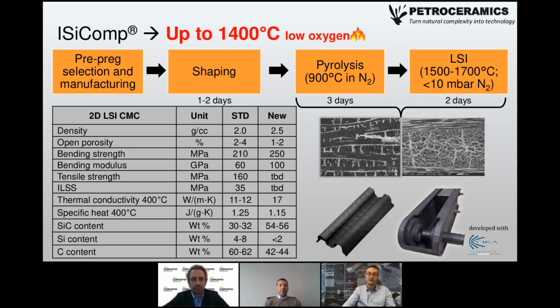So moving to higher temperature application, we have one of our leading trademarks, ISiComp. Also, in this case, we select the material and perform all the steps of processing from molding to conversion into a carboceramic matrix composite. In this case, after pyrolysis, densification is obtained by means of liquid silicon infiltration, which is faster and way cheaper than other ceramization techniques for these materials, such as silicon carbide CVI. The whole process lasts less than 10 days instead of weeks, for example. And also in this case, we can handle complex shapes and different dimensions.